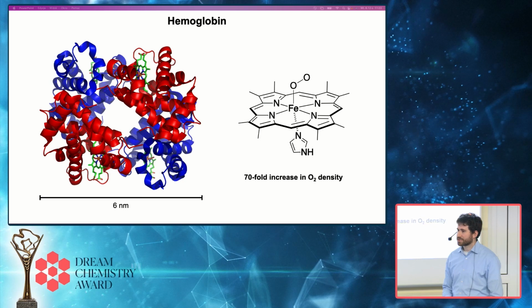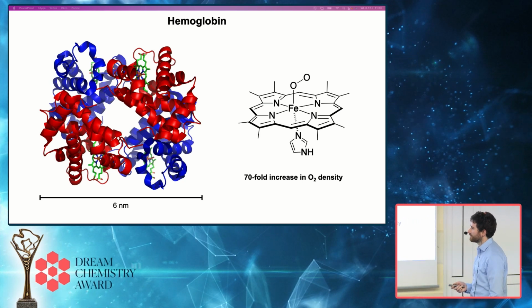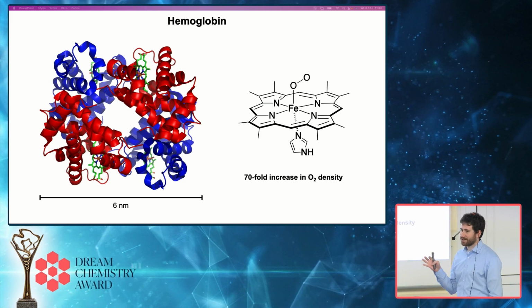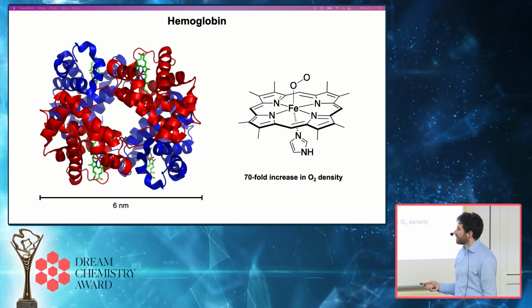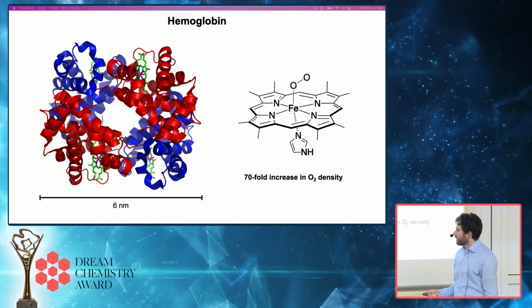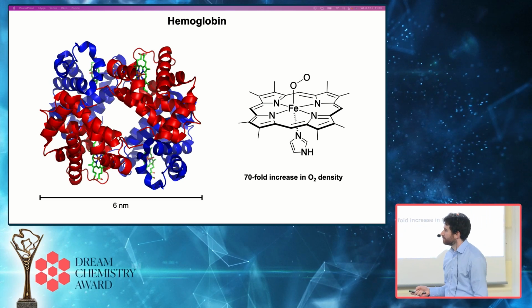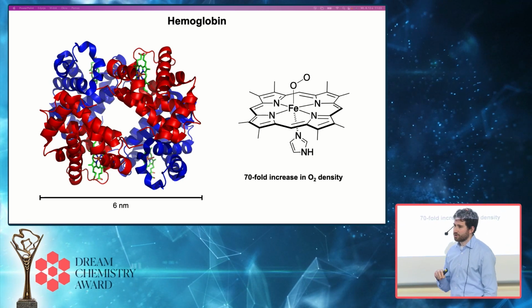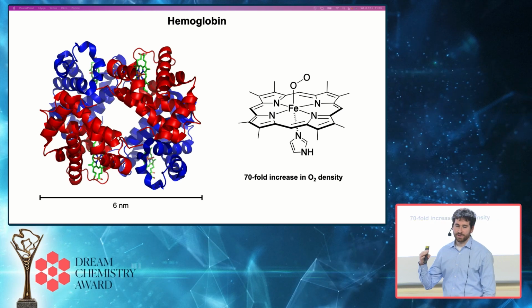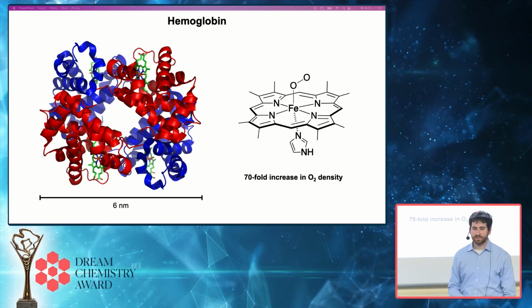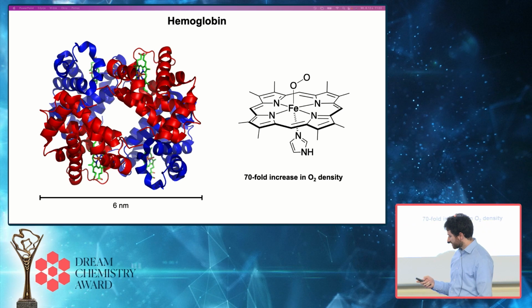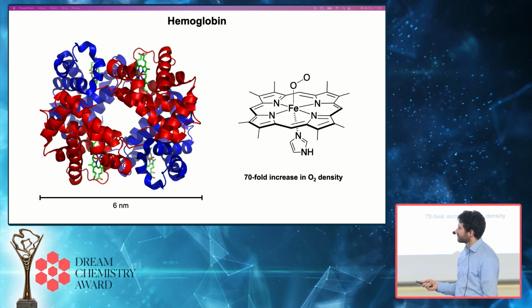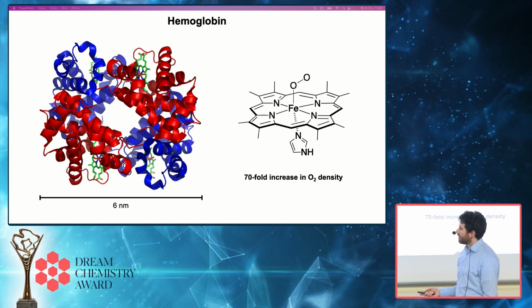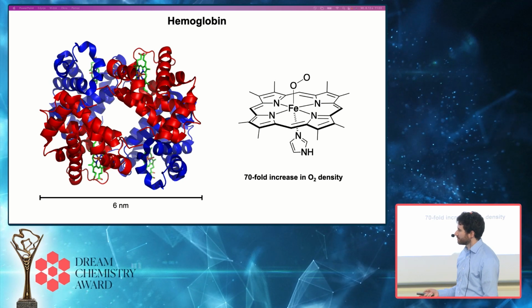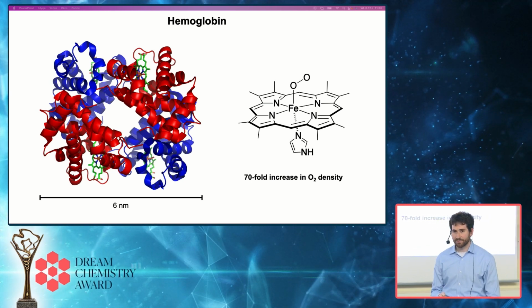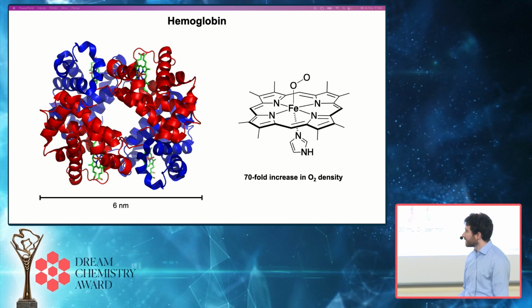And so hemoglobin, of course, contains iron porphyrins, which chemically bind oxygen and allow oxygen molecules to come together to much higher densities. So red blood cells have about a 70-fold increase in the density of oxygen compared to the amount of oxygen that's dissolved in water, because we're co-localizing oxygen molecules through this chemical bond between iron and oxygen over a much smaller distance than exists when they're dissolved in water.